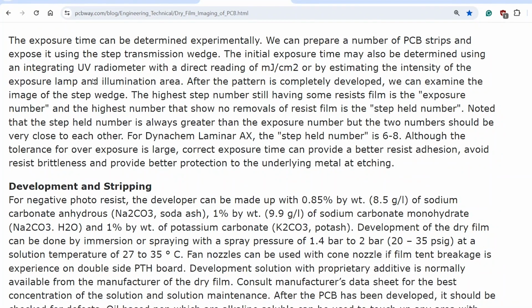You need to do experiments. You should have several PCBs, develop them, and find out which one is good. Then you go with some test patterns with fine details and inspect them under the microscope until you find the sweet point of your exposure. It's very important, especially in a DIY environment. You can't make very, very dark films. It's a problem. You can print with a printer, and that means your window of optimum exposure is narrow. If you use real photo film, where black is black and transparent is transparent, it's much easier. But in a home, DIY, non-professional prototyping environment, you have a pretty narrow window to find this optimum exposure timing.